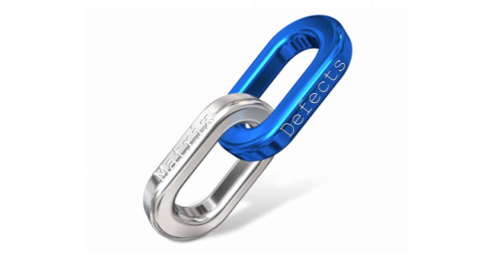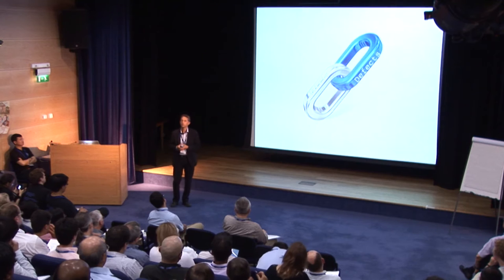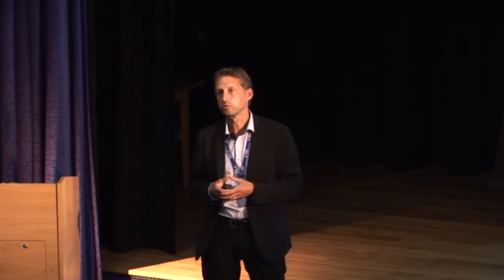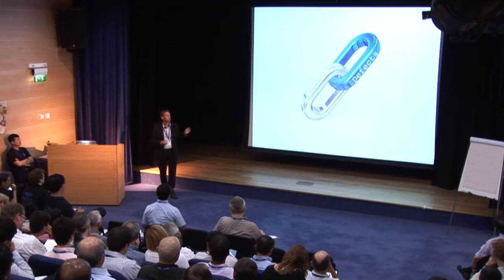So I made this picture, which I think is some of the essence. We have to consider the matrix and the defects, and we see that they also work together. I had a look at it a couple of times, and I think perhaps it's not quite right. It gives the impression, but what we've also seen is that the matrix may influence how a defect generates a fatigue crack. So it's a bit more complex, but I think it at least gives an impression that we have to take those into account.